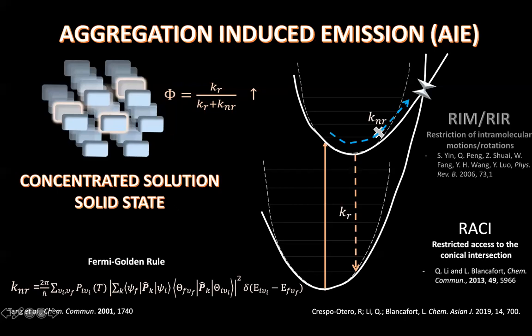What could happen as well? In some cases, and this is limited, it's not very common, but it also happens and has generated a lot of interest in the last few years, essentially because it's the opposite behavior. It's what happens when you put the system in the solid state, and instead of having a decrease of the emissive response, you have an enhancement. That essentially could happen because of the interactions with the molecules around the central excited molecule, which can restrict the access to these conical intersections, or decrease the overlap between the vibrational wave functions of the ground and the excited state.